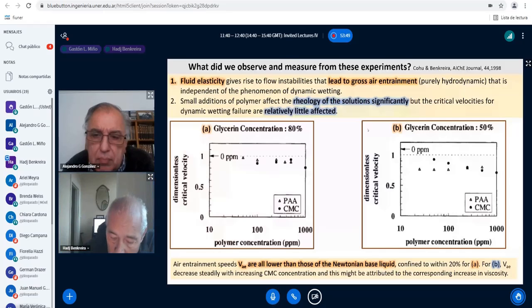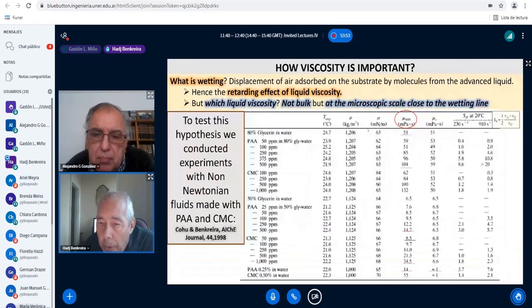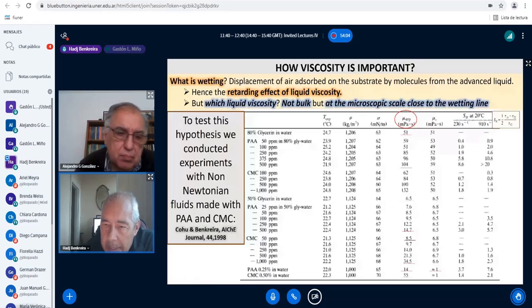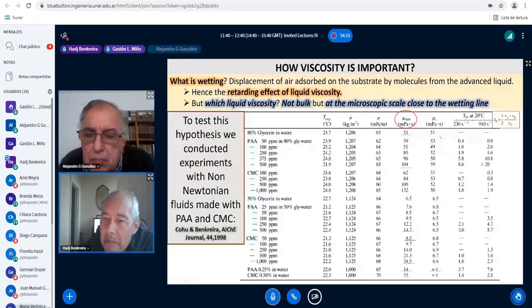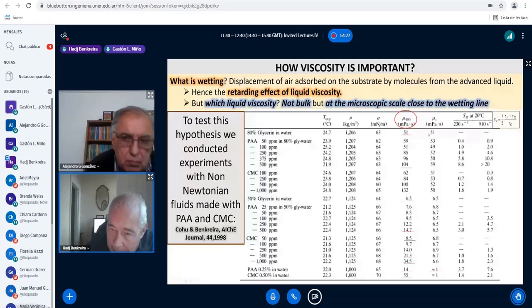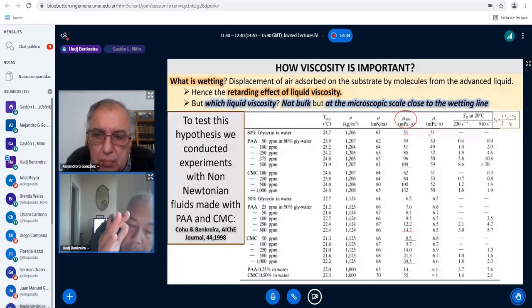No, it isn't. Not at infinite rate of deformation. The only reason we put in here the viscosity at high shear rate is because we were trying to find out which viscosity is important. And we realized it didn't matter, because the viscosity at high shear rate was the lowest viscosity that could be attained. But that lowest viscosity was still not as near as the viscosity of the solvent. But good question again, because strictly speaking, it isn't the low shear or the mu infinity of a shear thinning fluid. It is the solvent viscosity.